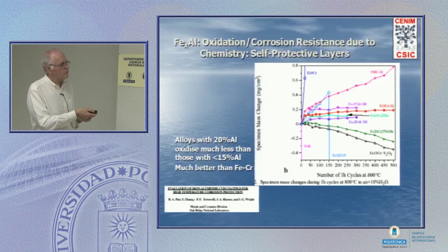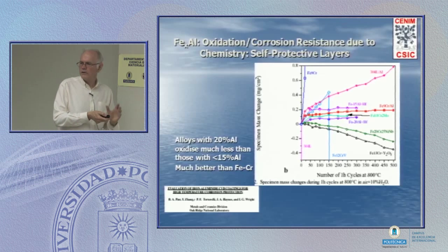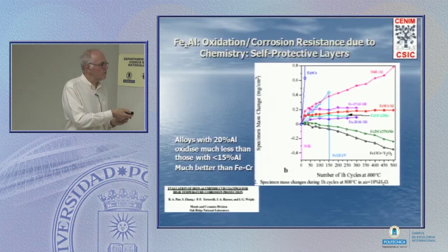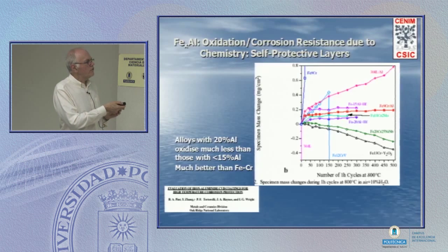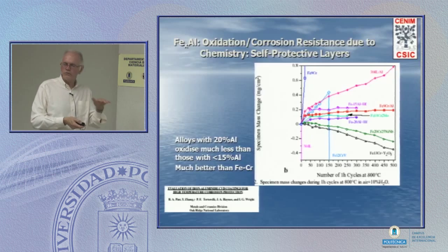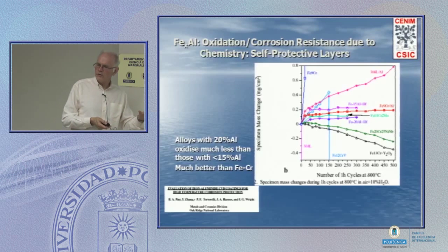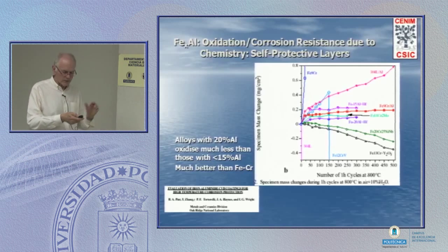Here's another example of iron 13 chrome with a little bit of yttria, and here it's oxidizing like mad, and the oxide is flaking away because of the thermal shock that we're putting on. These alloys here are all alloys that contain 15 and 20% aluminium. Adding in aluminium means that you oxidize, you form something like a nanometer thick oxide, alumina layer, and then you stop. You protect yourself.